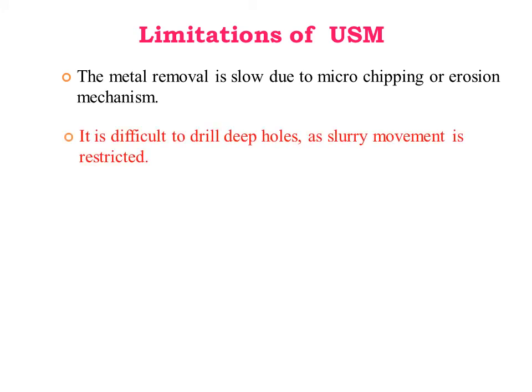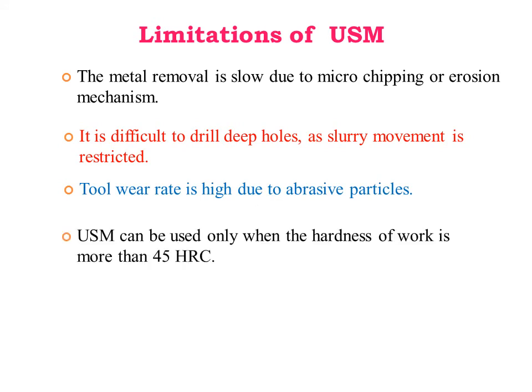Limitations of USM: the metal removal rate is low due to micro-chipping or erosive mechanism. It is difficult to drill deep holes as slurry movement is restricted. Tool wear rate is high due to abrasive particles. USM can be used only when the hardness of the work material is more than 45 HRC.